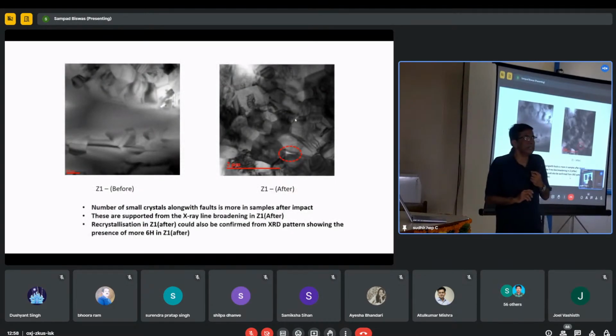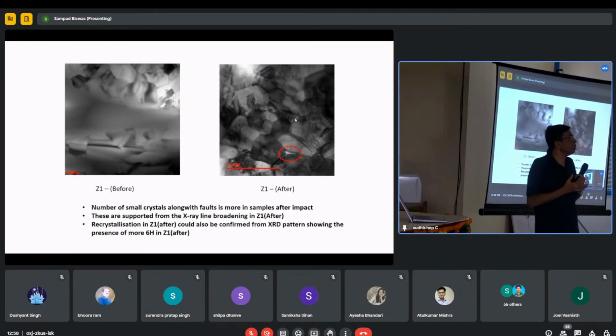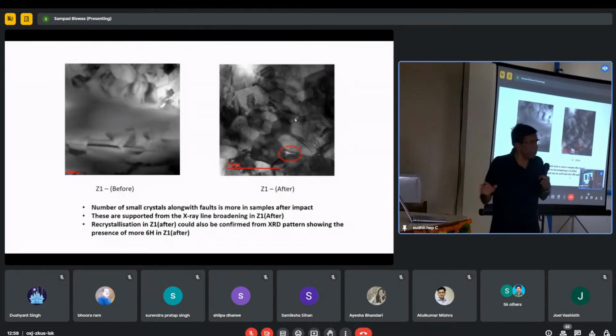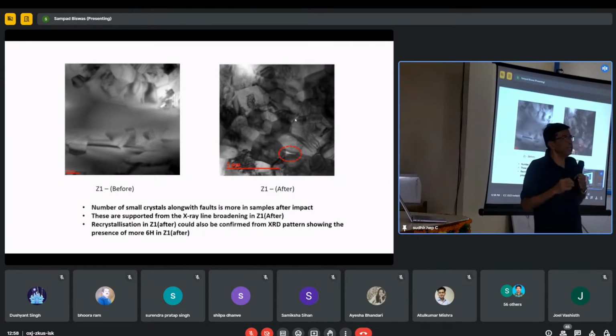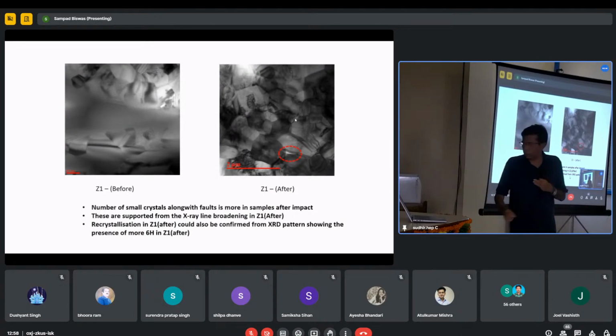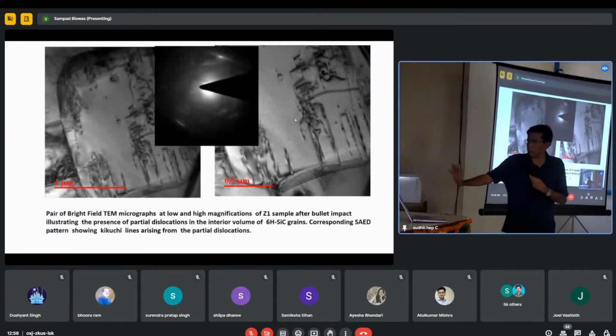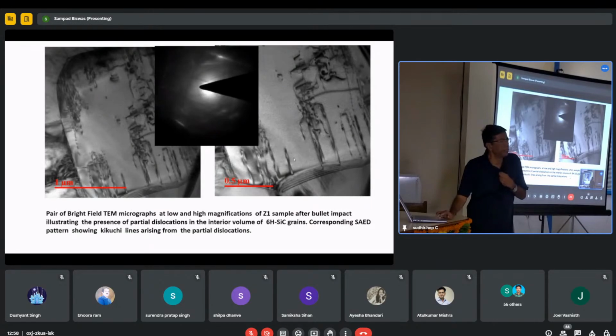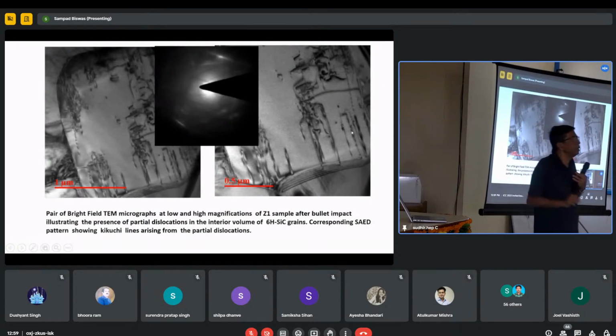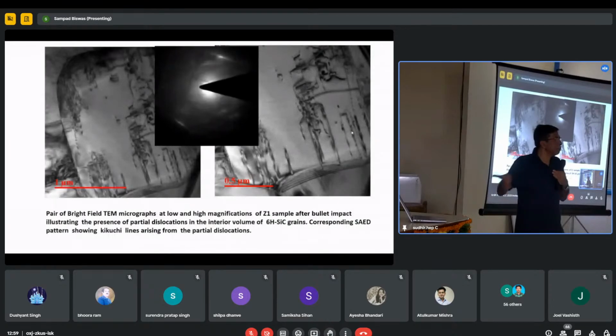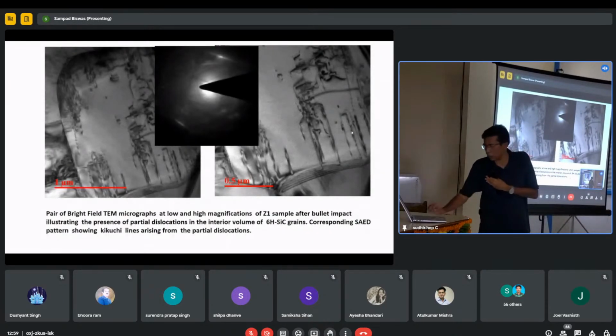What we wanted to say is that a lot of dislocation activities were there during the shock process, while these were in the plasticity region, and these dislocations create defects, which I am showing you. See, if you look at it, a typical Shockley defect, you can find one dislocation creating the defect here, the other dislocation creating another stacking fault here, a third dislocation creating the third stacking fault here. This is a typical Shockley defect created by the dislocation and by the shear stresses applied to this material during the shocking.